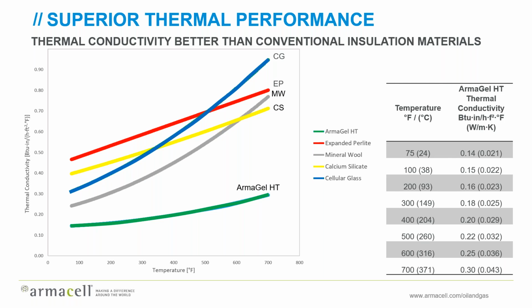Here's a graph of thermal conductivity against temperature. And the higher up the graph you are, the worse the thermal conductivity. And the further to the right you are, the hotter the temperature. So you can immediately see that thermal conductivity tends to increase with increasing temperature, but some materials increase faster than others. So for example, the blue line is cellular glass. The grey line is mineral wool. You see quite a steep increase in the gradient of their curves as the temperature increases. In other words, the thermal performance rapidly becomes worse. But the green line is for ArmaGel HT. And as you can see, it's far, far lower thermal conductivity than those other common materials that are used in industry. And that means that the insulation itself can be a lot thinner.